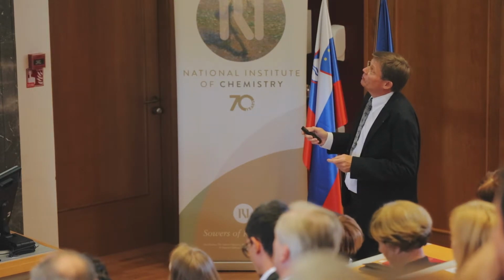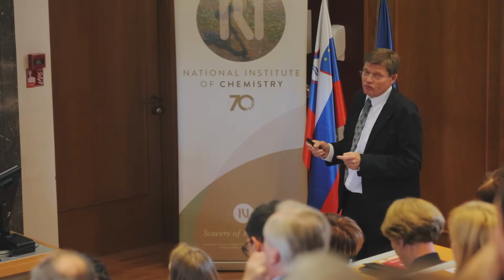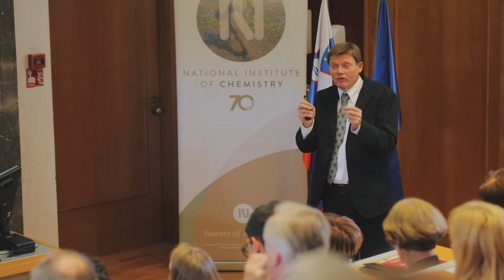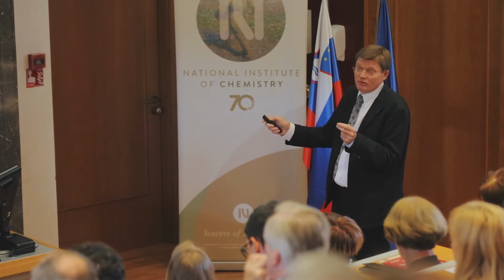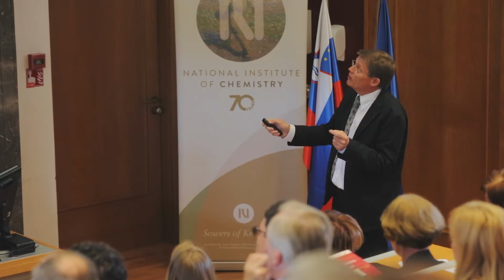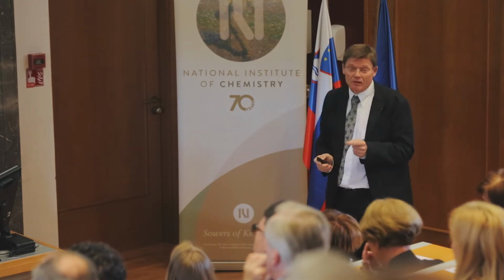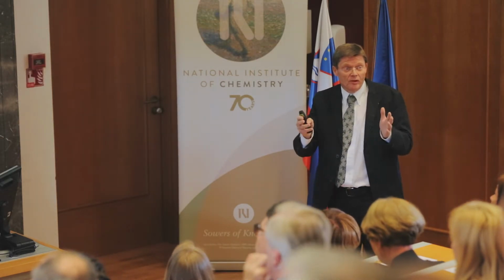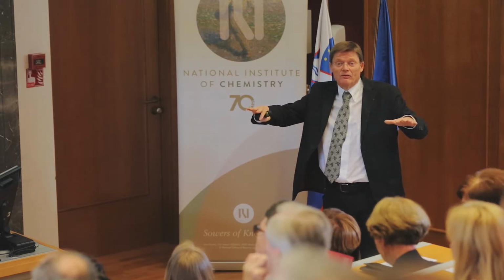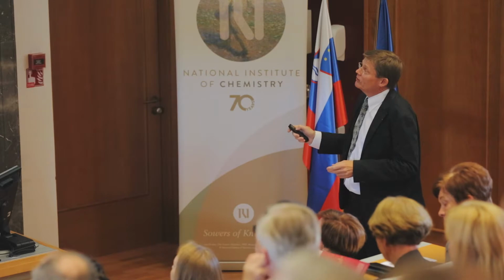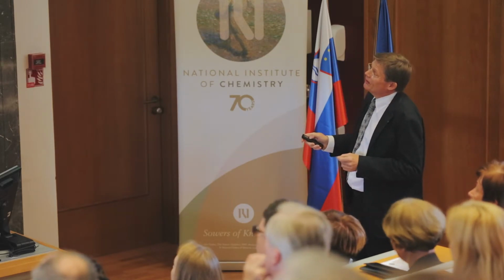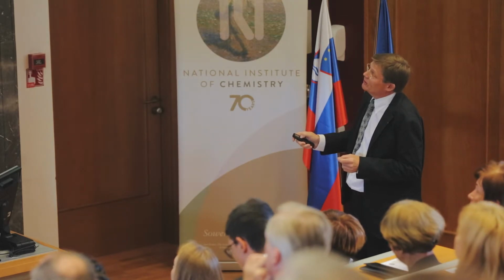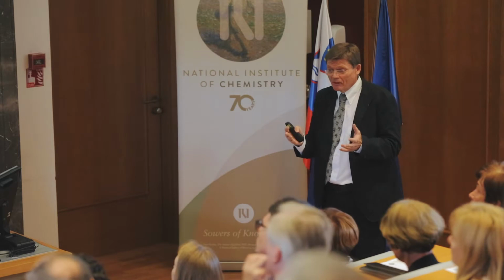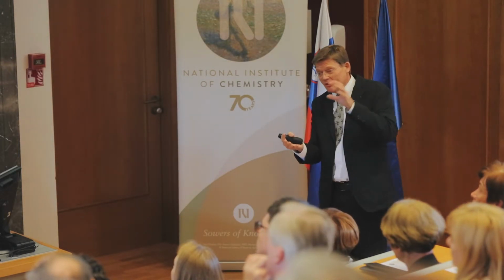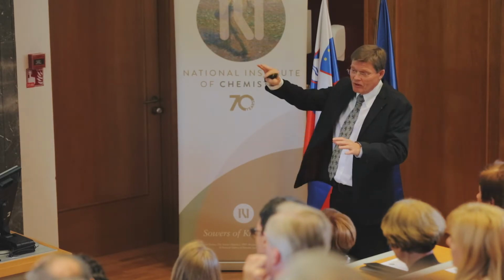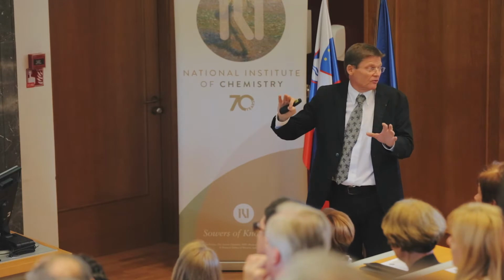So you can also do the following. You can plot, for example, now the electrons. And this is particularly good if you have a material which is a very, very good electronic conductor, like these kind of superconductors. So when you block the electrons by switching in zirconium oxide, which is a very good oxygen conductor, then you just do the opposite. When you block the electrons in steady state, you have separated out your ions. Looks like a very simple method, but practically it's very complicated because you have to seal. These are the different phases here. You have to seal this with respect to the outer oxygen atmosphere. When the oxygen has access, then it will directly level out the gradients you need to build up inside. Practically speaking, it's not so trivial.